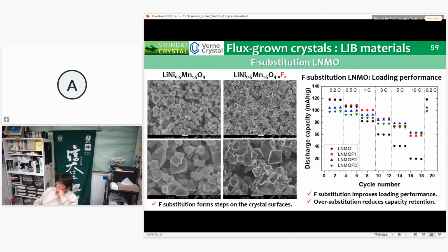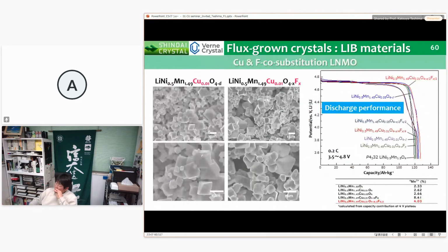Fluorine substitution can improve loading performances. From these pictures, it can be seen that the performance can be greatly improved. It was found that the co-substitution of fluorine and copper results in even better performances, like these pictures, like these figures.